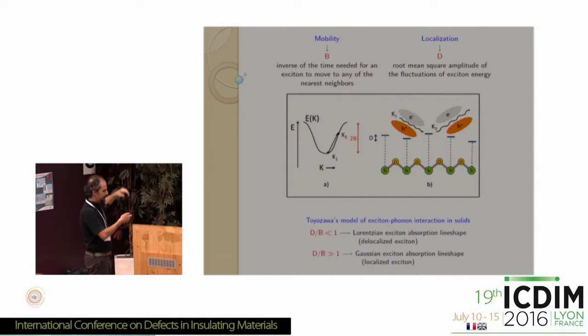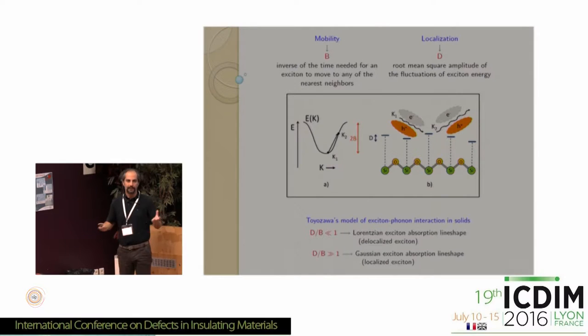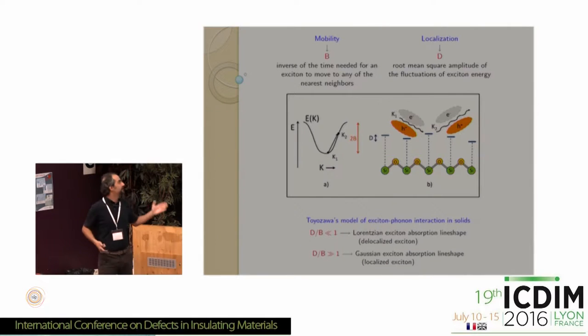And it can be shown that the width of this band, which is called B in this slide, is nothing else than the inverse of the time needed for an exciton to jump from site to site. So we can characterize exciton mobility with this parameter B. The larger B is, the larger the exciton band is, and the shorter is the time needed for the exciton to jump from site to site. So the more mobile the exciton is.